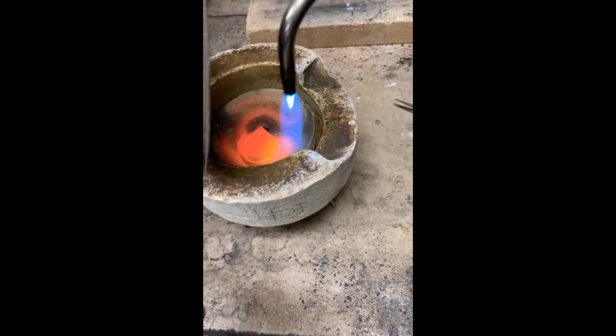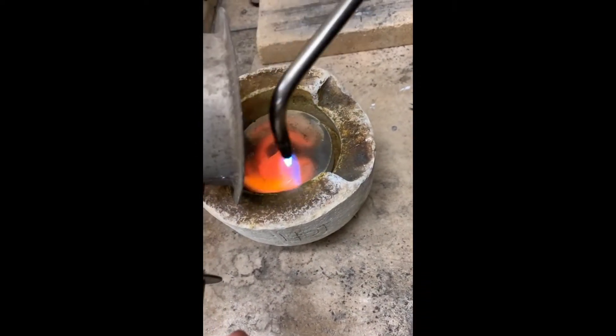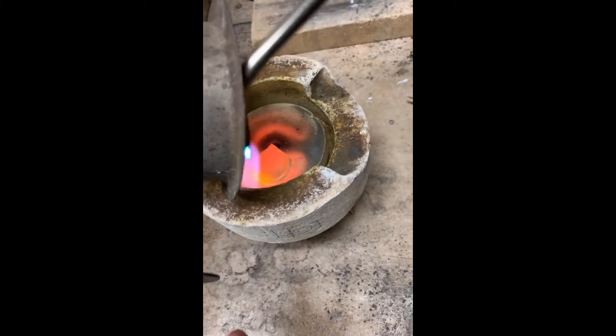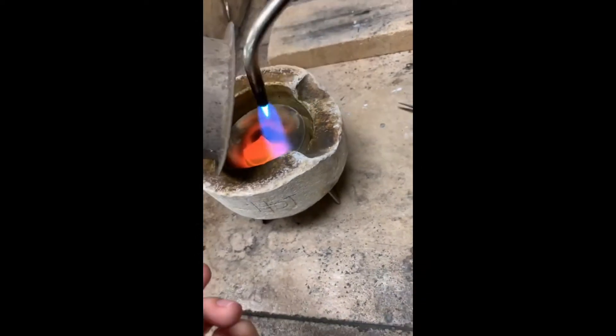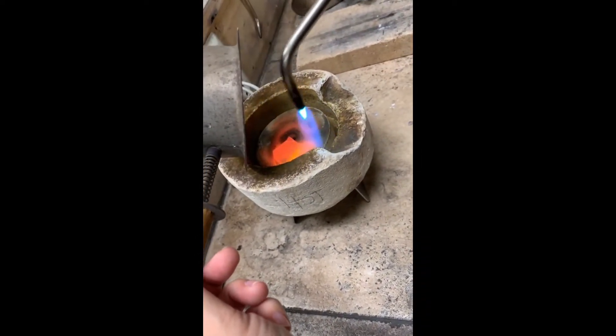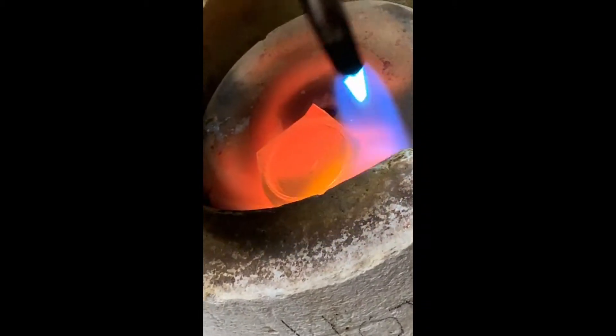That's the problem that most people have — they're hesitant, but that's what it takes. Because you need to build up the heat so that wherever the contact points are, they're brighter than everywhere else. So wherever that wire is touching the back sheet should be nice and bright. And that's where a nice hot kiln also helps to build up the heat.